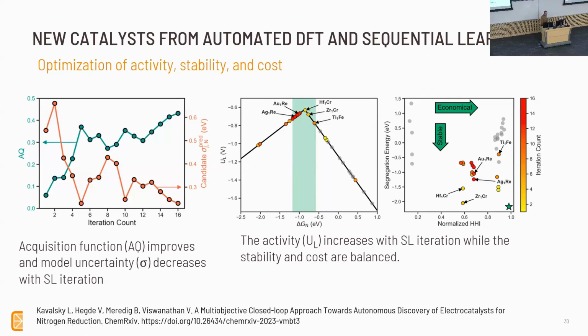So what we're basically showing is that not only are we getting closer to better performing materials as we go up in iteration count, but we're also reducing model uncertainty as we do it because we're using this kind of hybrid approach. And I think that's an important point to make, because if you want to try to find high-performing materials, you also need to be a bit explorative, a bit riskier in terms of trying to ascertain where these needles in the haystack lie. And then on the right are just two of the metrics for performance that we were looking at for this project. The color coding here corresponds to the iteration count, so you can see how it evolves as a function of the sequential learning iteration.